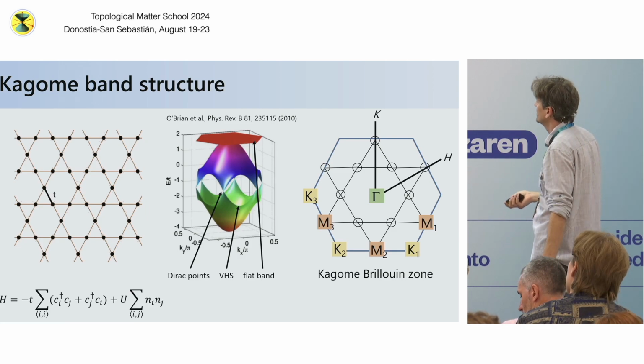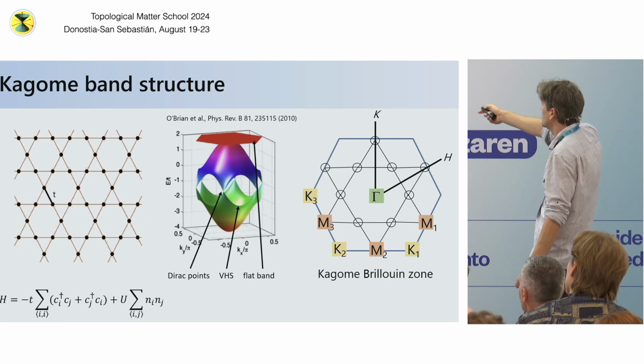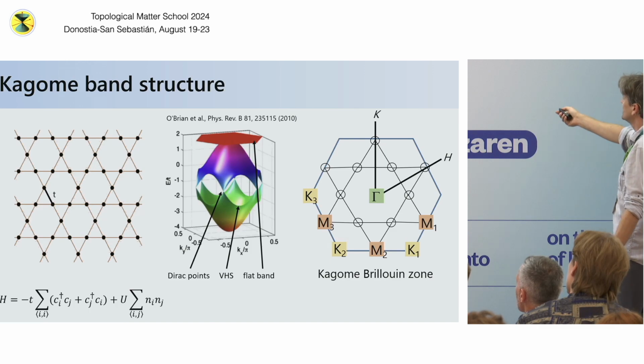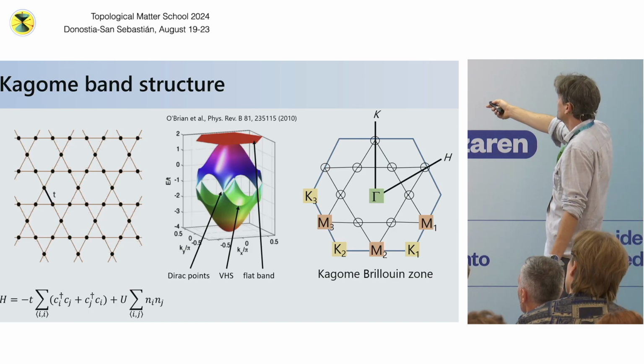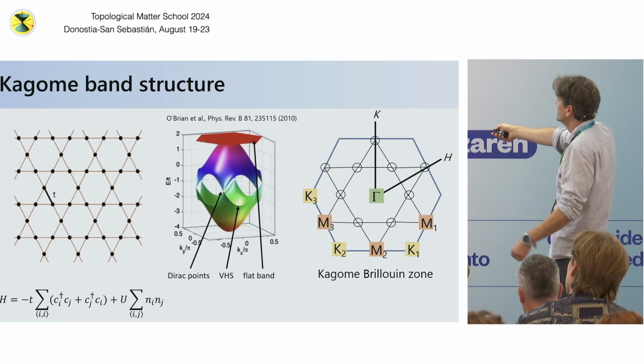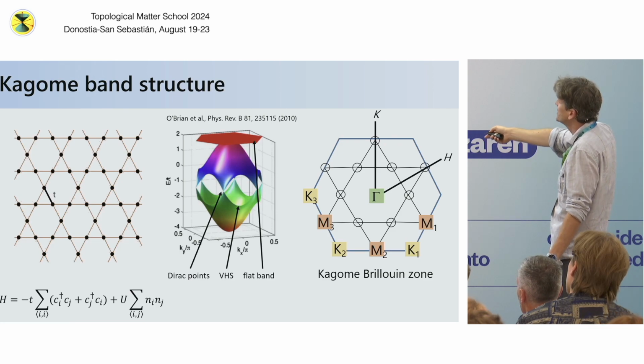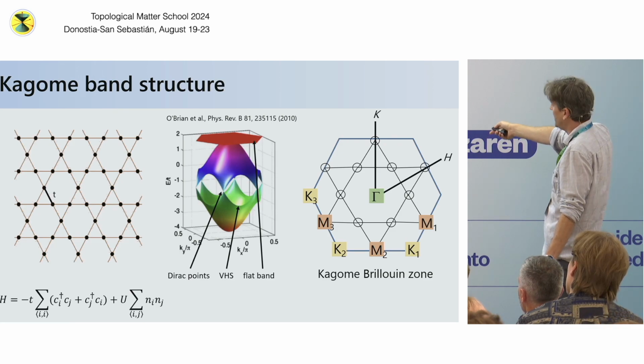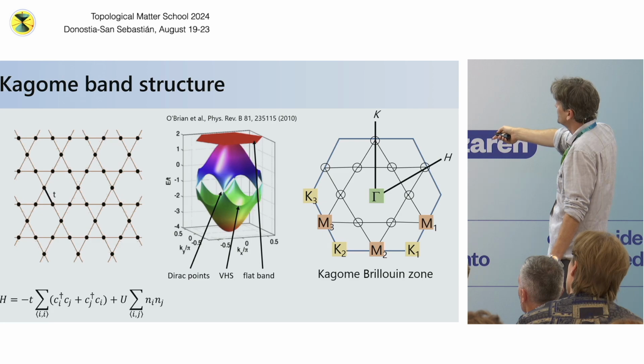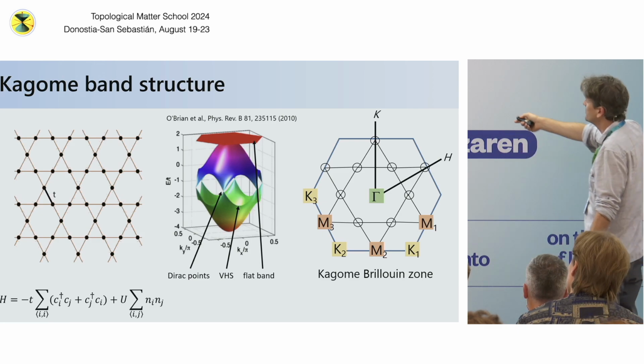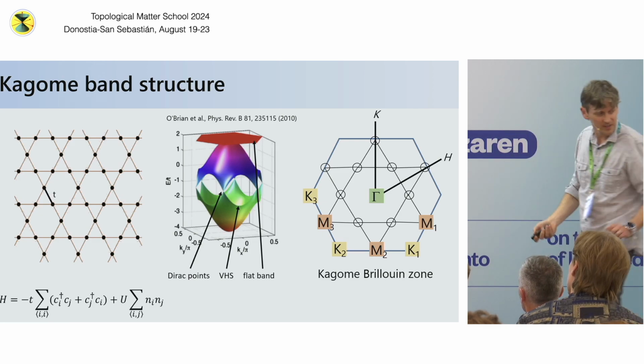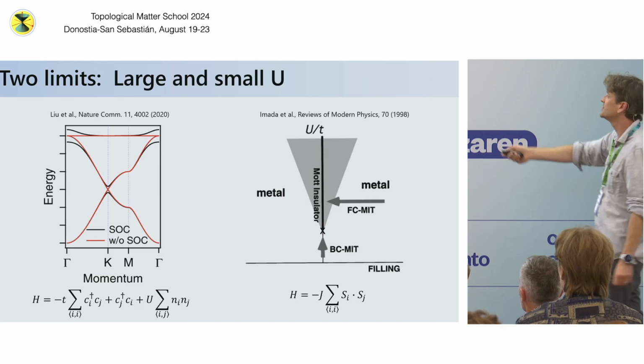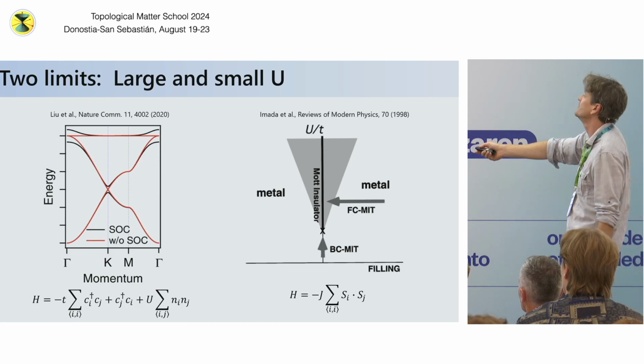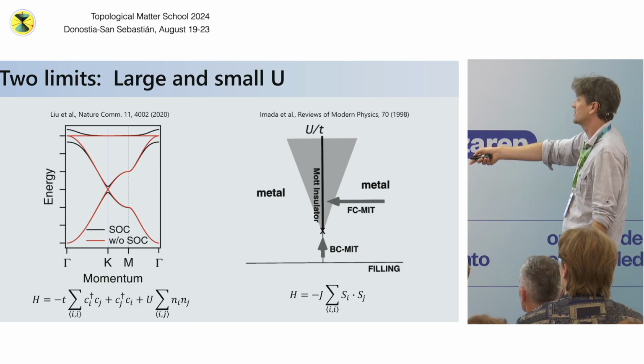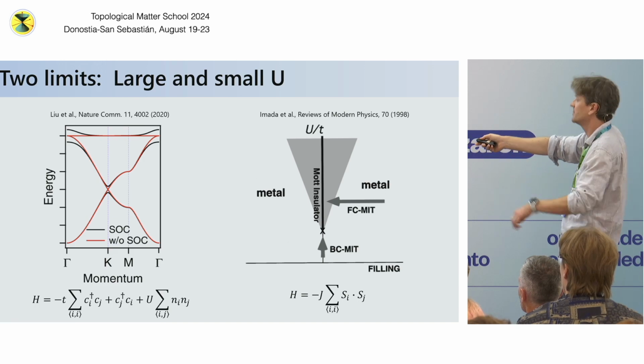And I'll talk about these three features in the band structure individually, but just as a calibration for people who maybe haven't looked at the Brillouin zone for a Kagome lattice or hexagonal lattice, just some terminology. When I talk about the M point of the Brillouin zone, that's the midpoint of the edge, okay? And if I talk about the K point, that's the corner, okay? And the gamma point is the center. And so one can do cuts along these high symmetry lines and visualize these different features that come from this simple tight binding model of the band structure of a single Kagome layer, okay?